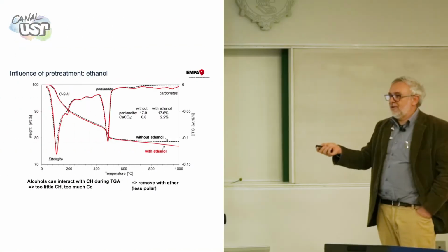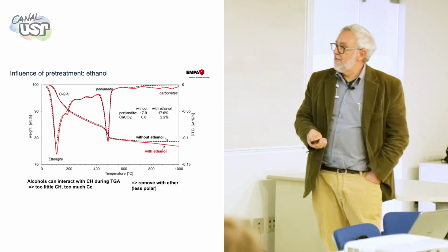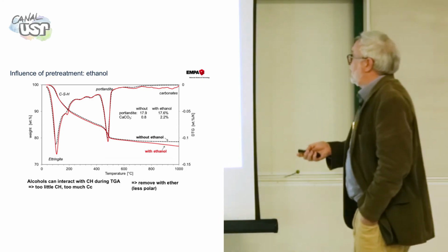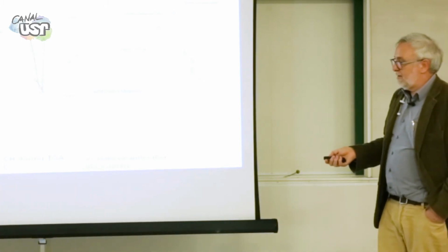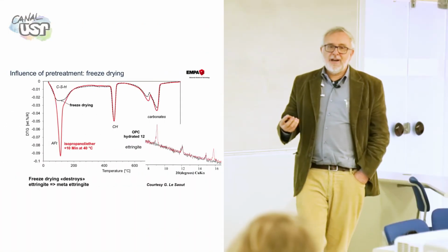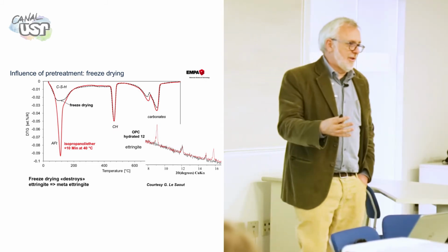I'm working with fiber cement that is reinforced with PVA fiber or PP fiber. And of course we have 70% of filler in it, but in the end we always have some carbonation. That is not really from the sample, it is a result of this reaction inside of the thermal balance. We have to live with that, at least we have to know. And here you should avoid ethanol. So remove with ether. Freeze drying, well, freeze drying is not a standard procedure. You can have different machines, different vacuums. It changes a lot and sometimes it doesn't work very well.